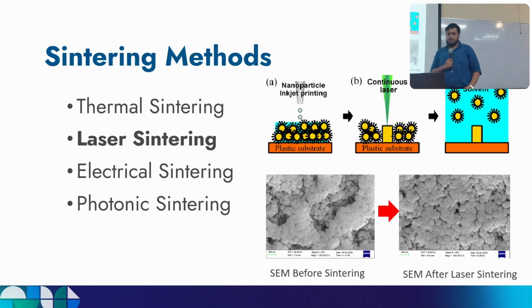So there are lots of methods in sintering flexible electronic circuits. The most conventional method is thermal sintering, where we just use a conventional oven and put the substrates and the printed materials inside the oven and keep the oven on for a few hours under constant temperature. But there are a few drawbacks in that, because the plastic or polymers that we use as substrates have much lower glass transition temperatures. So that leads to deformation and stuff like that if we heat to much higher temperatures.